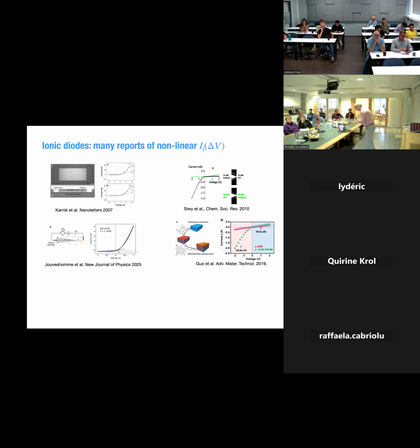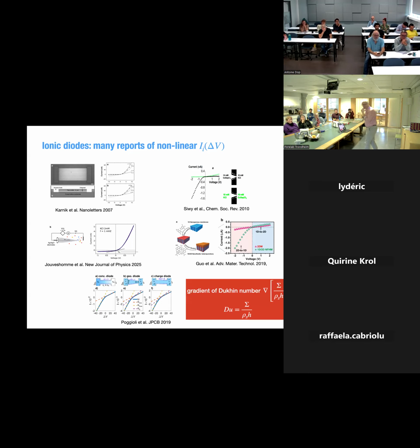And indeed, this phenomenon has been shown many, many times over the last 10 years or so. So this was the first one to show that, Karnik, where he had a system with two different coatings on the nanochannels. And you can see, indeed, it's a perfect diode. I mean, the reverse current is 0 and very high on this side. And actually, even with a single channel but conical, for example, it's sufficient to get PN-like behavior. And this is something we showed a few years back with a student, Anthony Poggioli, that once you have a dissymmetry between the left and right, you have a diode.